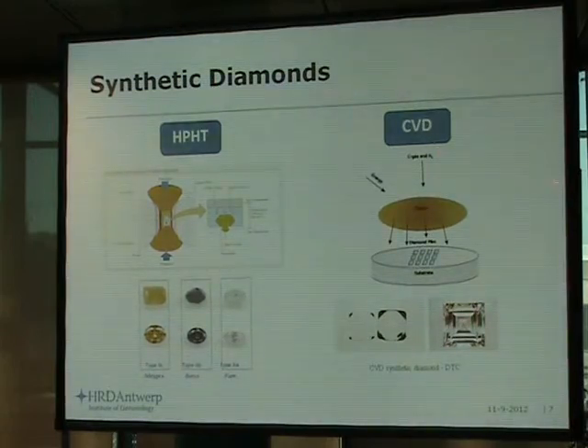The main focus these days lies on the chemical vapor deposition. It's a technique that comes from semiconductor industry, and essentially what you do is add a carbon source, most of the time methane gas, hydrogen into a plasma, so it's high energy, high temperature environment, and what you do is also grow layer by layer in a CVD reactor.